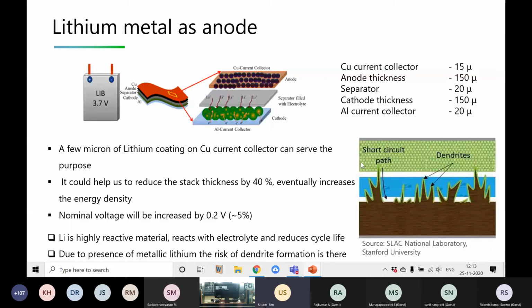So this is the anode and this is the cathode. So what happens in the case of fast charge? At that time lithium starts depositing on the top. Okay, and the next lithium, which is coming from the cathode to the anode during charging, is depositing on top of each other, and it forms a small spike of lithium from anode to cathode, and it's forming an internal short. Okay, so this is connecting anode and cathode, and due to this internal short, the cell can be short circuited internally, and it can go into thermal runaway. This is a huge safety risk, and that is the reason at present we can't use lithium metal. Okay, or we can't do a high charge in the case of fast charge with graphite.